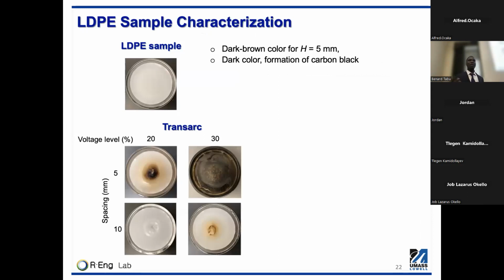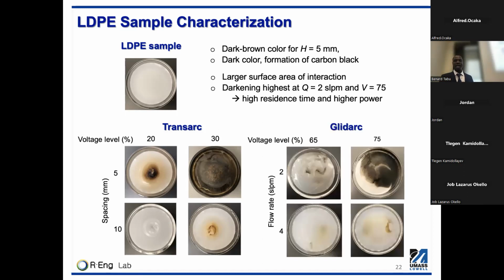So I also want to show you the sample characterization. This is using the optical camera. The pristine sample is white, very smooth on the surface visibly, but when you subject it to plasma, we see that for a shorter spacing there's enhanced interaction, which is higher at a higher voltage level of 30, because at higher voltage level you have higher power delivered onto the surface. Also, shorter spacing means the electrons travel faster with less collision, and that results in enhanced production. And for the Glidarc, we see that the interaction is more significant at the lower flow rate of 2 SLPM compared to 4 SLPM. At lower flow rate, we have less convective cooling, as well as higher residence times of the gas, which enhance the interaction.